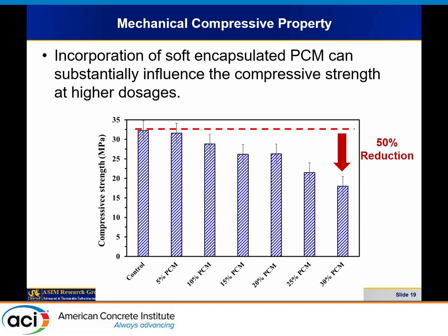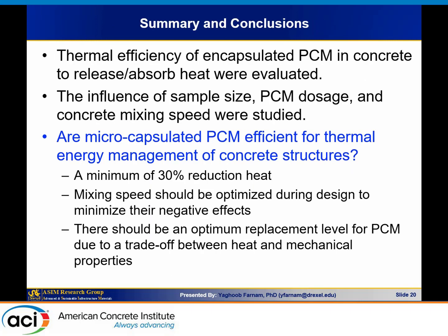We add PCM soft materials, you lower the mechanical properties. You get some advantages in terms of having some reservoirs in the system, or the thermal performance that you do get, but in the mechanical part, actually you might face some problems. So just to summarize what I talked about: the goal of the research was to understand the thermal energy of the encapsulated PCM inside the concrete. As I mentioned, there are some challenges when you put in microcapsules, because you could break them, you could have some chemical interaction, so you could break the shell, and it might not be efficient. So we wanted to see what the efficiency would be.